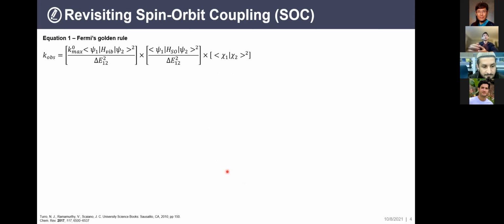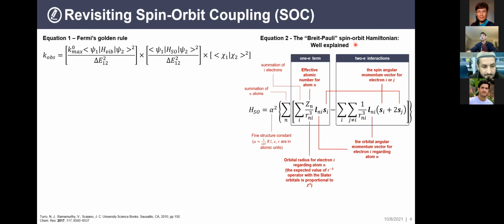And okay, so in terms of how to populate triplet states and how to let the triplet state emit the light, there is a phenomenon that's super important called spin-orbit coupling, because the electron needs to flip its spin during the emission process or the population of triplet state process. The rate of spin-orbit coupling is related, in quantum physics, to this Hamiltonian, and this HSO here is the so-called spin-orbit Hamiltonian. It is related to many different descriptors, but importantly, we have a Zn right here, and this R, which is the orbital radius, is also related to the atomic size.